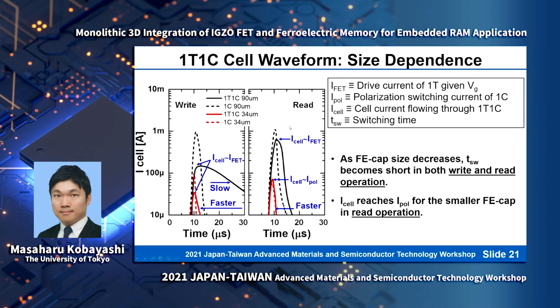We also studied the ferroelectric capacitor size dependence in this figure. As you can see, when you shrink the cell capacitor size, we can make faster switching compared to the larger cell capacitor. So these results are basically consistent with our first estimation of the switching current in the first introduction page.